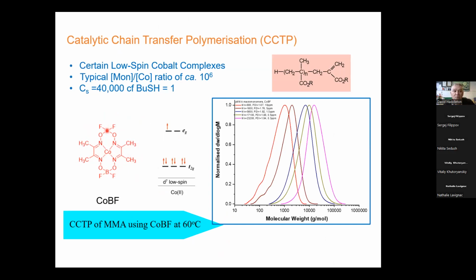So this catalyst is stable at pH 1 at 80 degrees centigrade, which is quite amazing. Without the boron, you can use it with methacrylates in organic solvents, but as soon as you add some acid, the catalyst will fall apart. And for those of you who want to remember your inorganic chemistry, cobalt 2 is d7 low spin. What's quite important, if you're looking for a catalyst, is that you have to have d7 low spin. We don't actually know why it has to be low spin, but if you change these ligands to oxygens, they'll go high spin, and they won't work in this way.